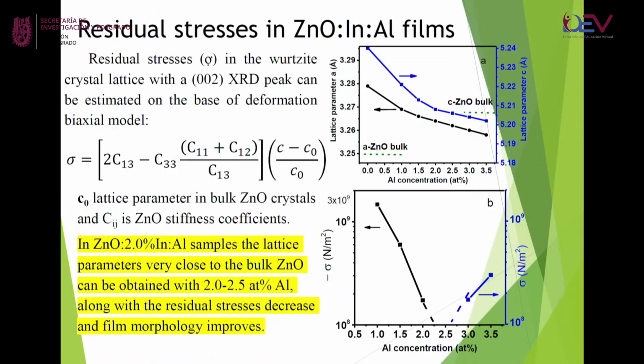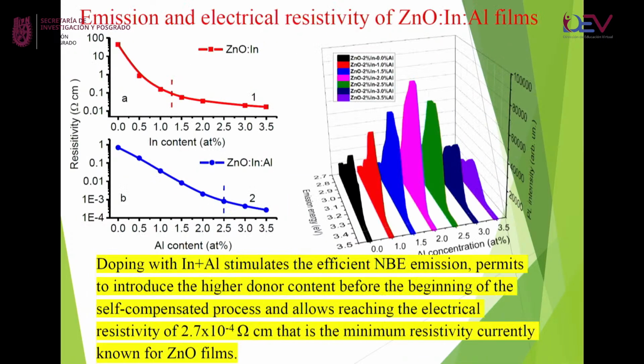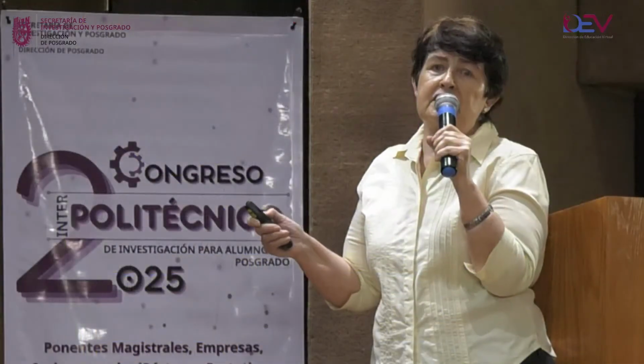And you could see this result. We calculated the stress and showed that for this definite concentration, the stress practically changes to a very, very low level. Simultaneously, you could see here that for this definite concentration, photoluminescence increased dramatically because the crystal does not have any tension and has an ideal crystal structure.